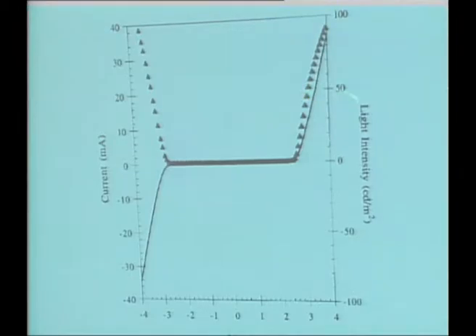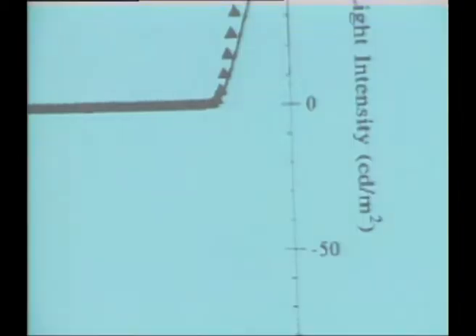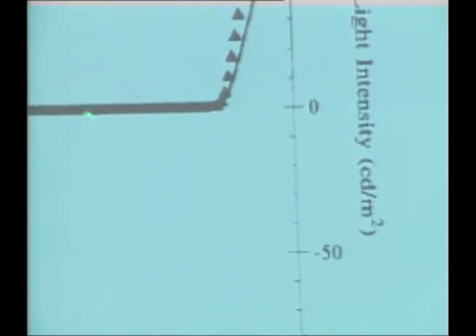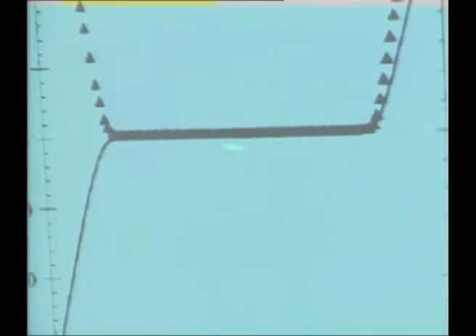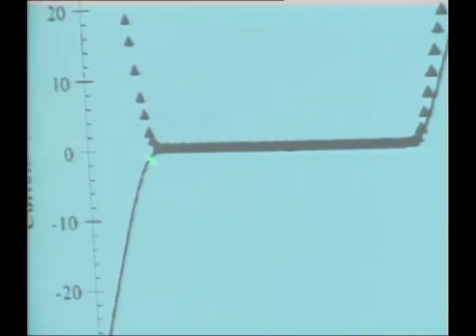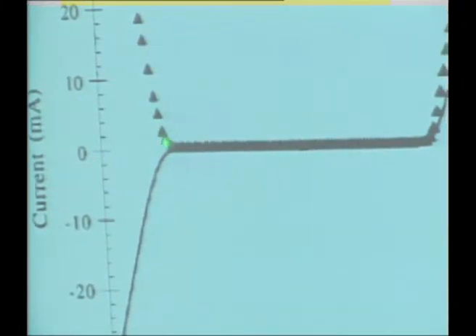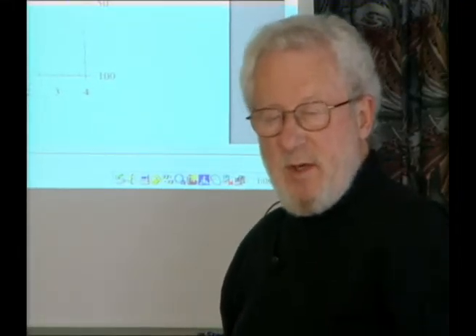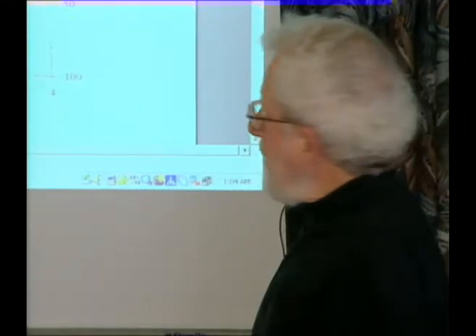There's light coming out here, light intensity in candelas per square meter. Here's as a function of voltage. This is the current, okay? If you go in the forward direction, you get no current until you reach a voltage which is large enough to pull an electron out of one side and put it in the other side, to redox the polymer. And now you go in the opposite direction, and again you get no current until you get to the symmetric voltage, and then it turns on. Of course, the current is in the opposite direction because I'm reversing the bias.